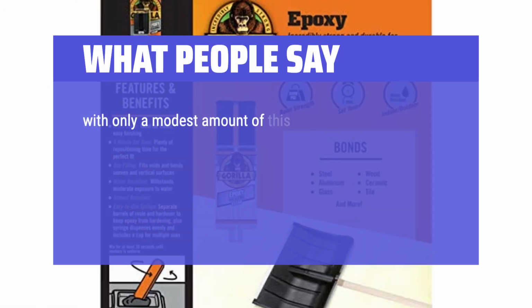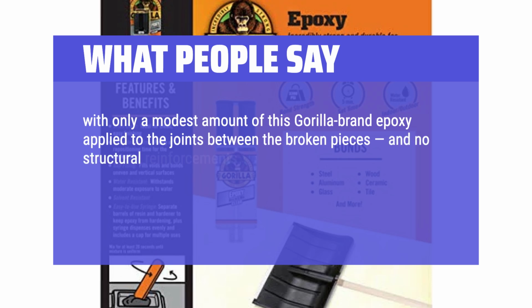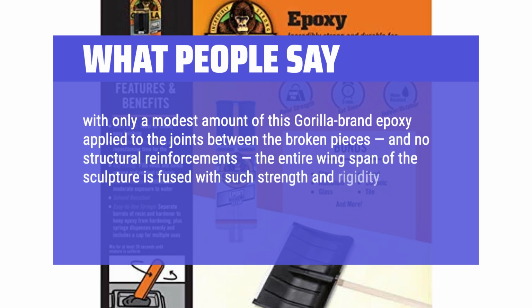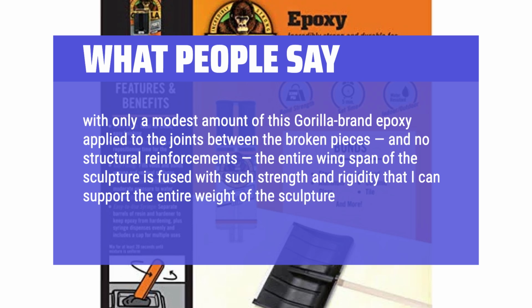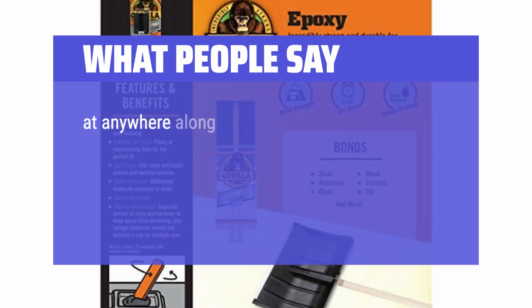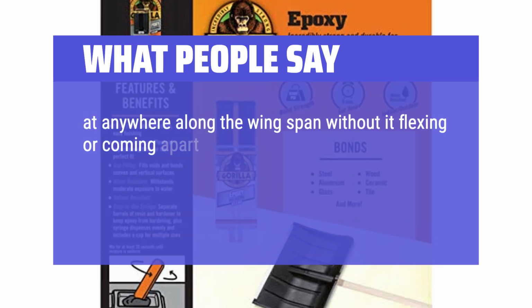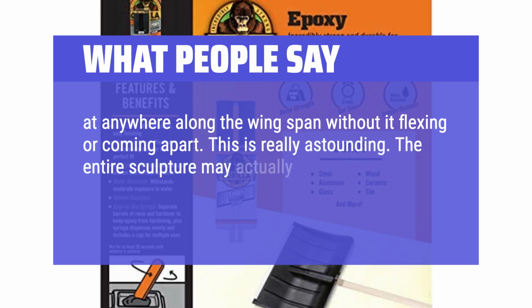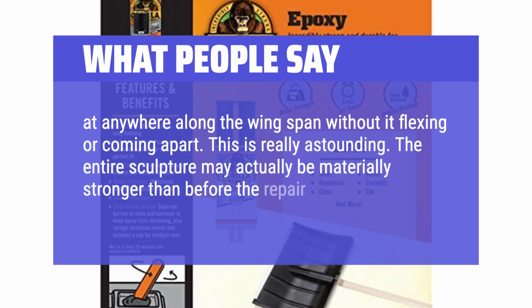With only a modest amount of this Gorilla brand epoxy applied to the joints between the broken pieces, and no structural reinforcements, the entire wingspan of the sculpture is fused with such strength and rigidity that I can support the entire weight of the sculpture, 80 pounds, at anywhere along the wingspan without it flexing or coming apart. This is really astounding. The entire sculpture may actually be materially stronger than before the repair.